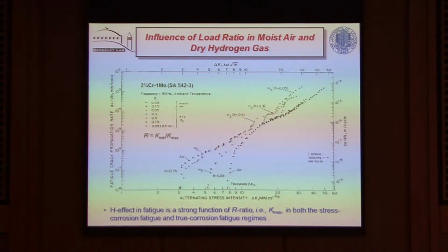And if we look at different load ratios here, the details aren't too important, but you can see this superposition point now is shifted along the delta K axis and simply reflects the balance in the cyclic versus the monotonic loads. So although we lack data in high-pressure hydrogen, we understand this process, and this can be used to generate these kind of so-called da/dN versus delta K curves, which then become the basis of prediction of life for a given component.